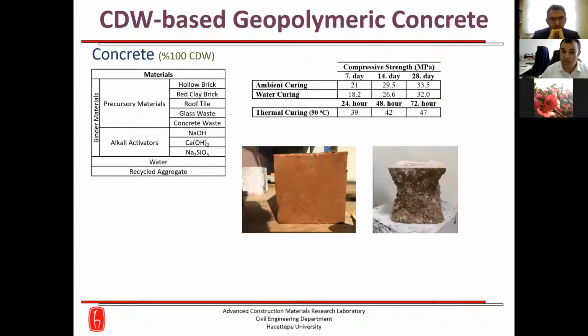We also developed concrete mixtures. These are concrete mixtures with 100% construction demolition waste, with both the paste binder phase and the aggregate phase directly obtained from construction demolition waste. And in these mixtures, we were able to obtain a strength higher than 30 megapascal under ambient curing. That's great. Under high thermal temperature, around 90 degrees centigrade, in 3 days, the concrete strength is going to be more than 47 megapascal. But in ambient curing at room temperature, we can easily obtain 30 megapascal, which is similar to the typical properties of normal strength Portland cement concrete mixtures.